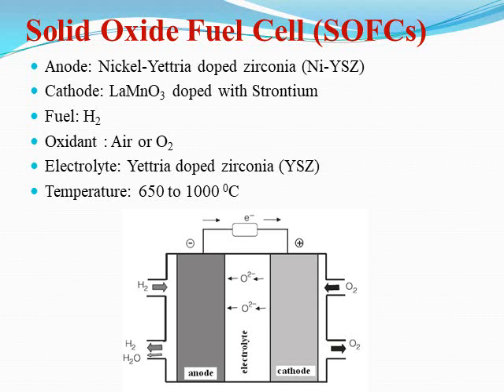The next fuel cell is the solid oxide fuel cell, generally called SOFC, also referred to as a high-temperature fuel cell. The anode material is nickel doped with yttria-stabilized zirconia (YSZ). An appropriate amount of nickel — 5%, 10%, 15% — is doped into YSZ powder and made in the form of an anode.